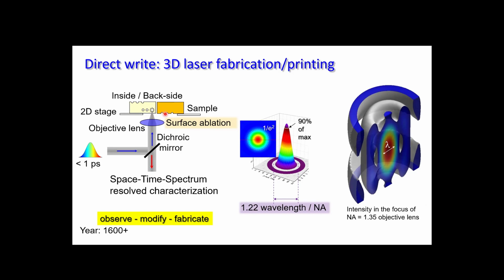So this is a slower way of modifying materials. However, considering this average power, which also tells us that the laser irradiation comes at very high frequency, we can scan and write, we can split the beams, we can do it in parallel. So this technique can be scaled up to faster throughput. But just to demonstrate principles, we are using something very simple. This is simply a microscope development. After 400 years, we are now using it for fabrication rather than just observing micro objects.